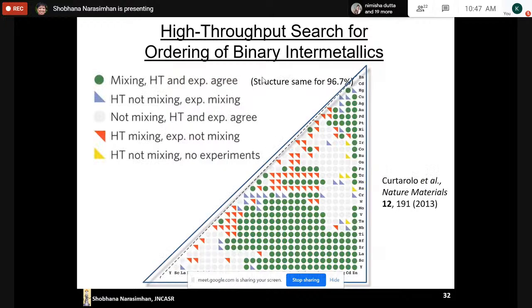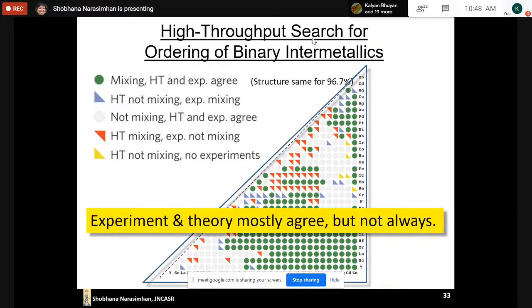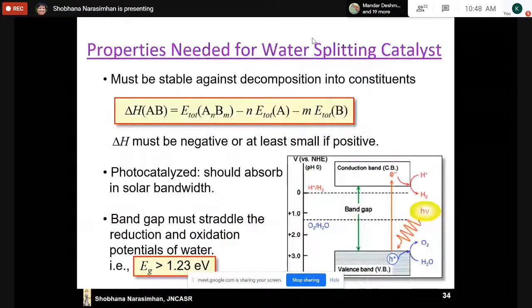And here, if it's a green circle, it means that both experiment and theory tell you that they mix. If it's a gray circle, which looks sort of white on the screen, it means that both experiment and theory tell you they do not mix. And you see that most of the triangle is either green circles or gray circles. And so the calculations are pretty exact for most of it. But there are some red triangles where the calculation tells you that they mix, but the experiment tells you they don't mix. So it is a fairly accurate technique, but it is not perfect. The experiment and theory mostly agree, but not always.